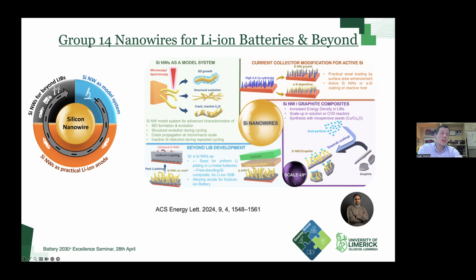So the approach here is as a stepping stone towards the 100% silicon anodes. So what you can do is, rather than growing these wires directly from the current collector, you can grow the wires from graphite. So this is a nice, reasonably high surface area material, and it also has the benefit of being electrochemically active as well. So you can potentially tune the composition of your silicon graphite anode materials to get the desired performance and mitigate some of the really excessive volume expansion that you would see in pure silicon anodes.